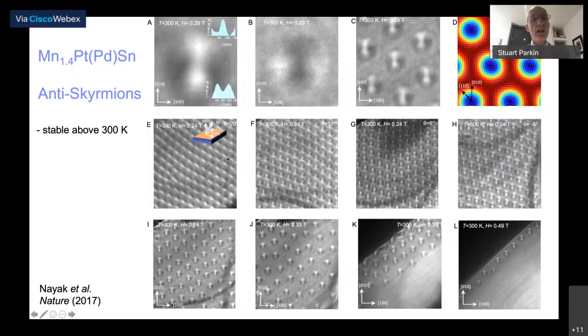And so if you look here in A, you can see this cloverleaf structure, which again is the image we see in a Lorentz transmission electron microscope mode. We see this cloverleaf pattern in this Heusler, which is a manganese platinum tin based compound. And we published this in Nature 3 years ago. Now it turns out that we can see these individual anti-skyrmions, but typically they form an array. So if you look in part C, you can see here a hexagonal array of these anti-skyrmions.